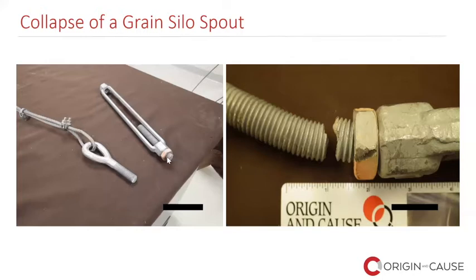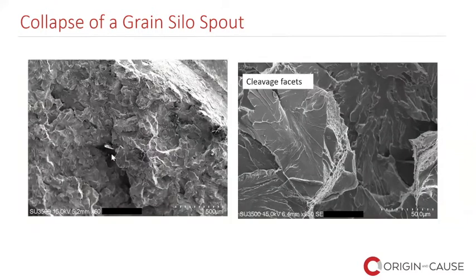In a fractured component, the mating fracture surfaces are usually mirror images of each other. We cut a small sample from the turnbuckle and we took it to a powerful microscope called a scanning electron microscope. Scanning electron microscopes allow examination of components at magnifications up to 30,000 times or even more. We don't need that much magnification in our investigations, but these instruments are capable of very high magnifications. And the images obtained under the SEM tell a lot of useful things.